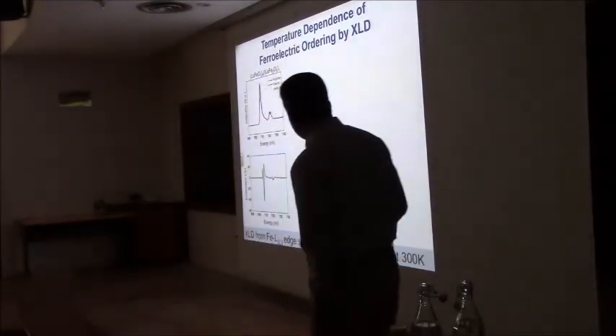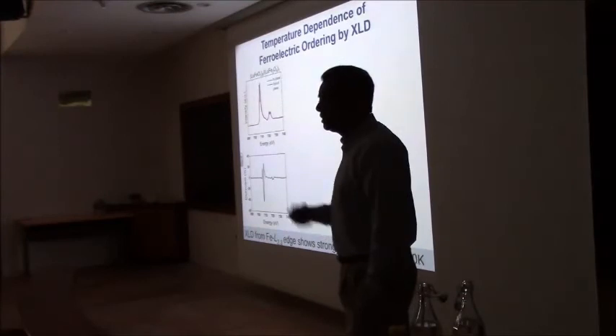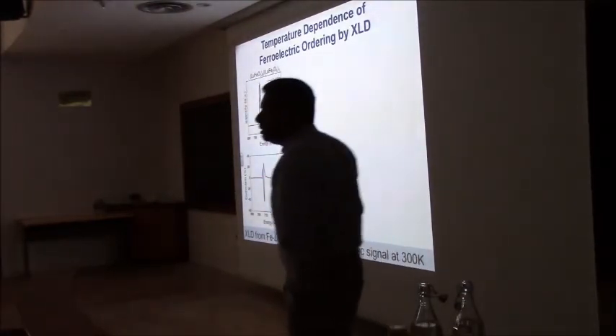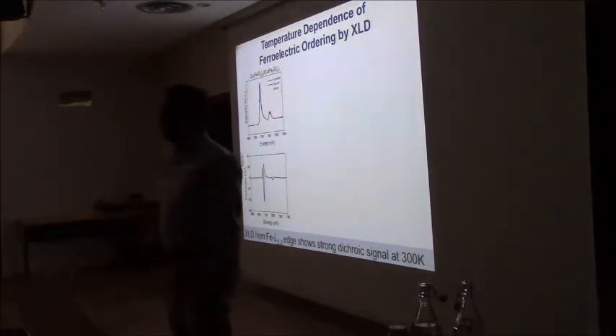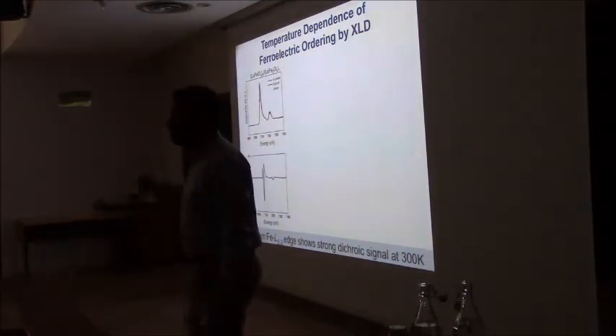Okay, now to find out about the ferroelectric order. It's not that easy to measure the ferroelectric order. We're still making device structures and stuff like that. But we can use, again, X-rays to probe ferroelectric order. In this case, we're measuring the linear dichroism, which is a good measure of some structural asymmetry in the system. And this one is for the 9 to 1. You can see the in-plane X-rays polarized this way versus this way.